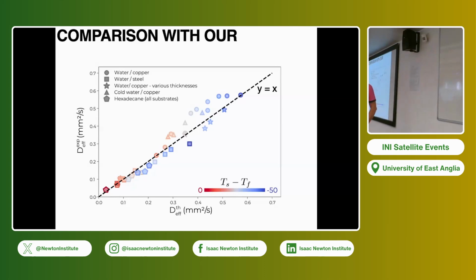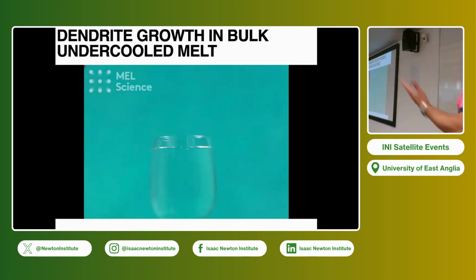And just to make sure there is no adjustable parameter, you know all the thermal parameters of water, the diffusivity in water and in ice, the effusivity, and all this stuff. And basically, we found a good agreement. Okay, so this is one way where we can see ice growing.